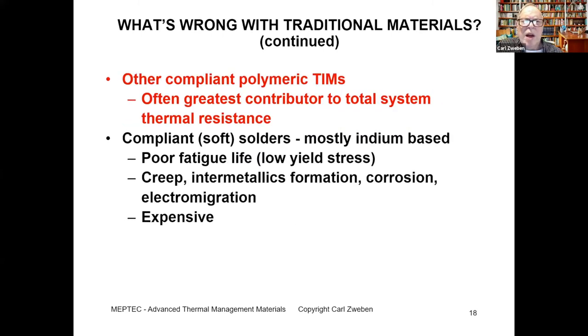There are many other polymeric compliant TIMs or compliant polymeric TIMs. And what we find is that they are often the greatest contributor to total system thermal resistance, which is a major problem. If we look at soft solders, which are compliant, mostly indium-based, because they have a low yield stress, which is why they're called soft, they have poor fatigue life. They're also subject to creep, intermetallic formation, corrosion, and electromigration, and they're fairly expensive.